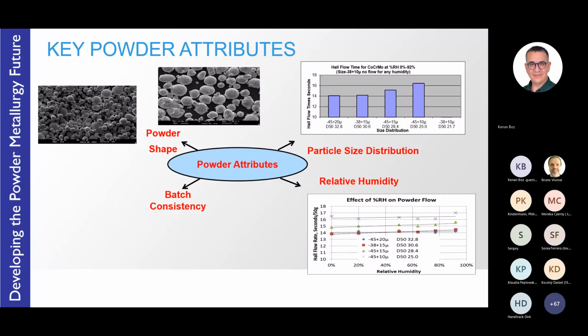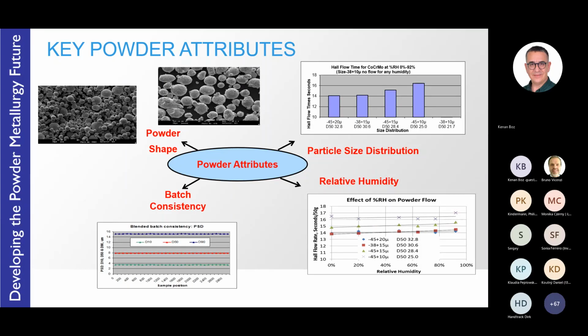And then batch-to-batch consistency. This can be for both size distribution and also the chemistry, and I've highlighted here oxygen content, for instance. And the starting oxygen content can have an influence on the use of the powder in service during laser powder bed fusion. After a time, of course, it will pick up more oxygen. So having low levels of oxygen in the initial powder sometimes is an advantage. And that's where vacuum melting in particular can be very attractive.